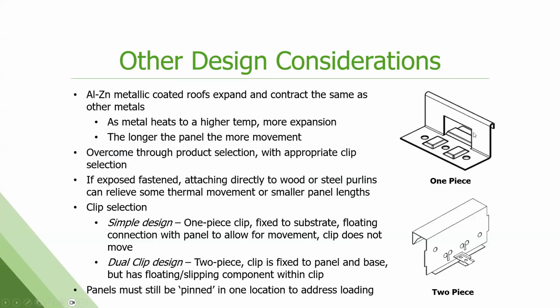Other design considerations. Aluminum zinc expands and contracts the same as other steel products, galvanized products. But again, you want to use a clip configuration, a floating clip, depending on the spans that you're doing and how it's attached. If you're doing exposed fastener and attaching directly to wood or steel purlins, that can relieve some of the thermal movement on smaller panel lengths. Here's an example of the two common types of clips that we see for concealed fastener. A simple design is a one-piece clip. That clip is fixed to the substrate underneath. The panel is attached to it with a floating connection, which allows the panel to move, but the clip does not move. With a dual clip design, you can have two pieces, a clip fixed to the panel and base, but with a floating component within that, so the clip itself can move as well as the panel in that configuration.